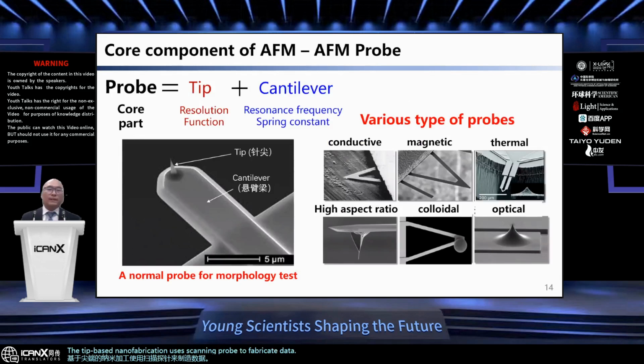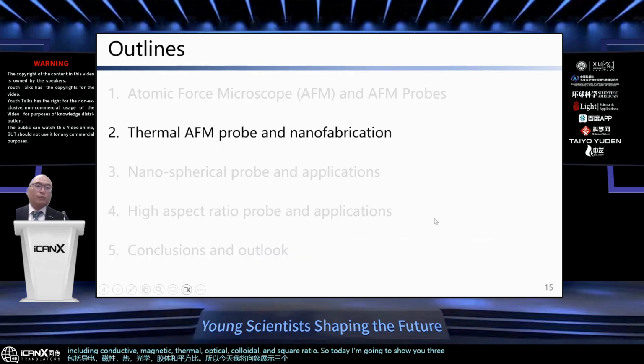So the core component of AFM is the AFM probe, similar to that shown here. It consists of a micro cantilever, normally made of silicon nitride, and a tip. The tip determines the resolution or the function, whether it's conductive, and determines the spatial resolution. And the cantilever determines the resonant frequency and the spring constant. Depending on the application, there's a variety of probe types, including conductive, magnetic, thermal, optical, colloidal, and high aspect ratio. So today I'm going to show you three of these special probes. First is the thermal AFM probe and its application.